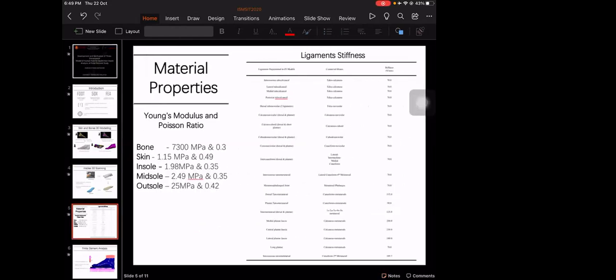So in finite element analysis, every element and model needs to be assigned different material properties. Here you can see that to the bone we assign 7300 megapascal and 0.3 Poisson ratio. Skin with 1.15 megapascal and 0.49 Poisson ratio. Insole with 1.98 megapascal and 0.35 Poisson ratio. Midsole 2.49 megapascal and 0.35 Poisson ratio also. And the outsole, we assign 25 megapascal and 0.42 Poisson ratio.